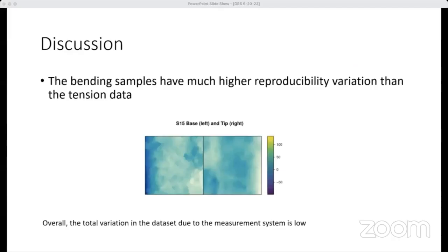One explanation for the difference in results between the tension and bending data is due to the physical differences that exist in the sample. So for example, I have just one bending sample listed here below. We can notice that on the base and on the tip, there are two sort of large cliff-like features that are present in many of the bending images that we could look at. However, this cliff is not always present in both the base and the tip. For example, the base could be shifted over slightly to not include this cliff. And the result is that there is going to be a low correlation between the two pairs of images, since this large cliff-like feature is going to sort of dominate the frequency bands that we are looking at.